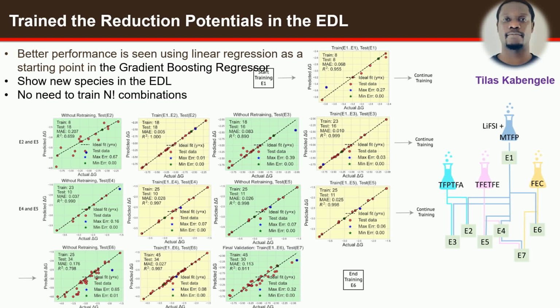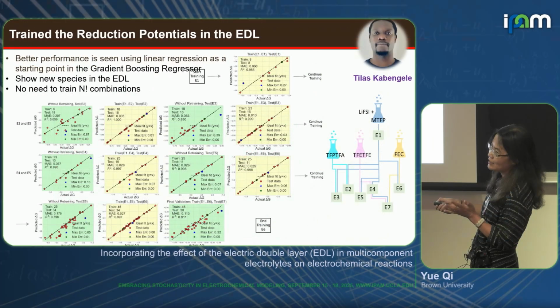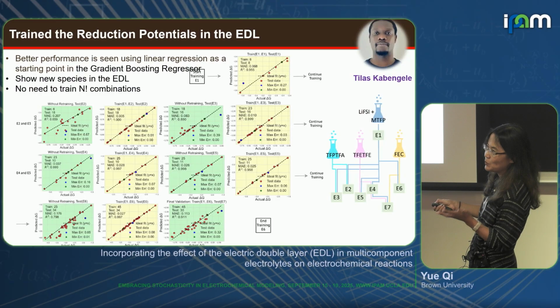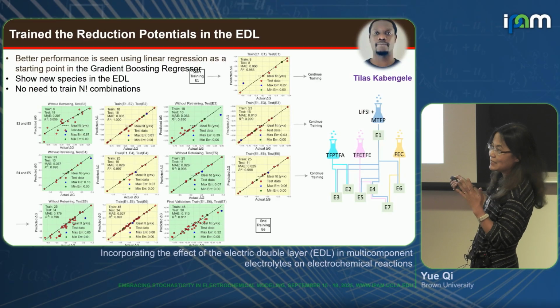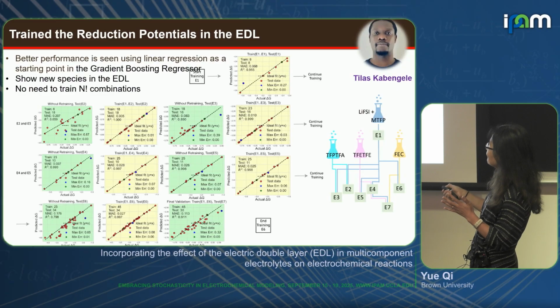So we blindly train the reduction voltages for our first electrolyte, and then see if they can predict the second electrolyte. It doesn't, so we retrain with the second electrolyte. And we move to the fourth electrolyte here, and it worked really well. I don't believe it, and say, well, you didn't train this, but those diluents did not come to this double layer, so they did not impact the reduction voltage that much, right? So we get another solvent, they really come to the surface, and then you have to retrain them again.